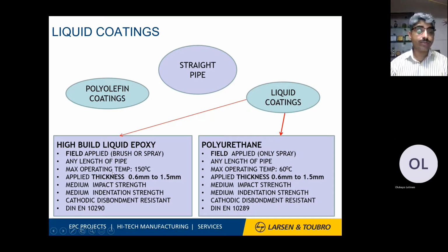So any length of pipes, the maximum temperature resistance is 150. The thickness range available is 0.6 to 1.5 mm, and all the properties are the same as before. So good strength, impact, indentation, and cathodic disbondment resistance. So these are the things which are important for us to address for the liquid coatings also.